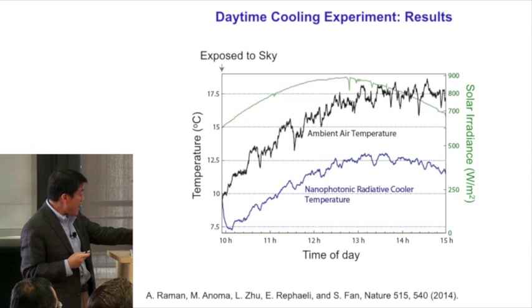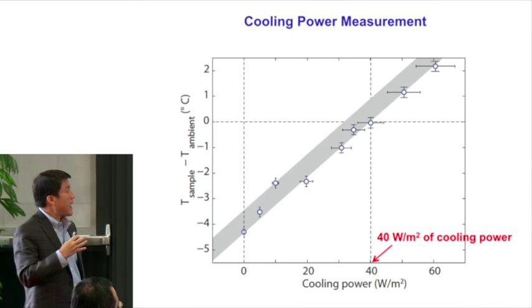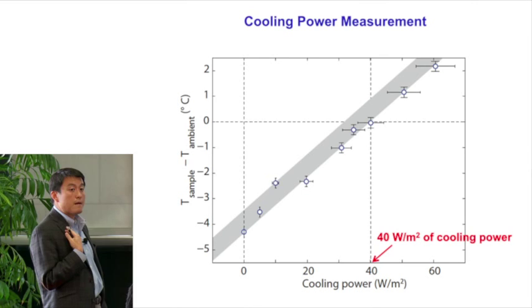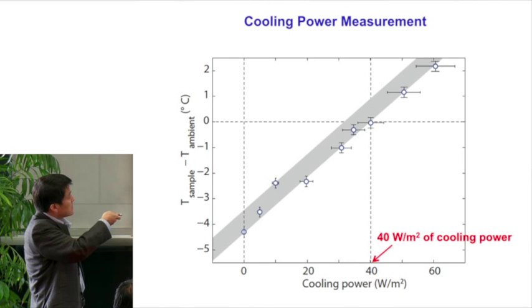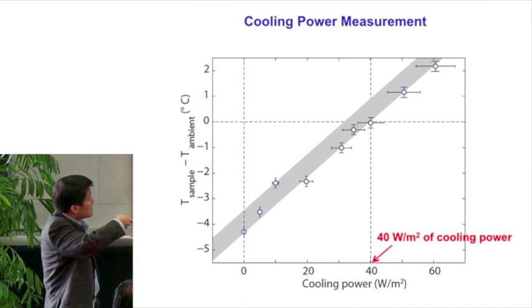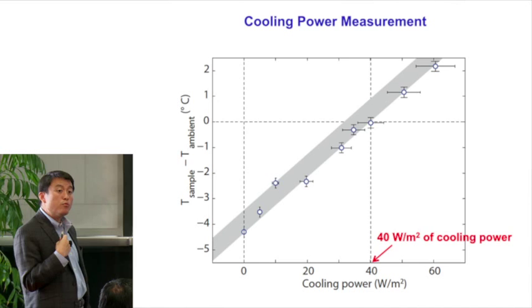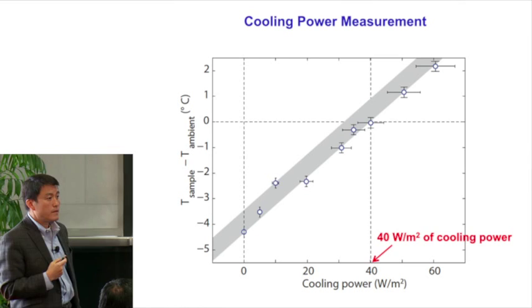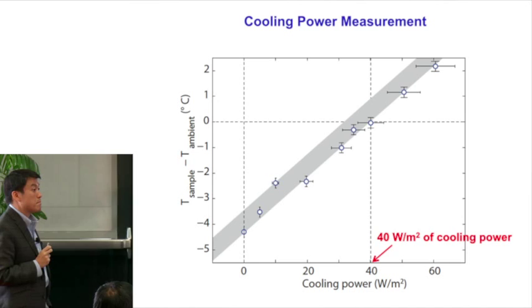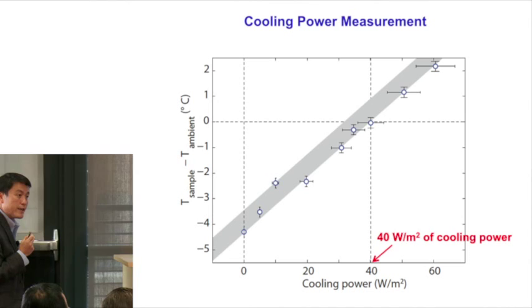We also did a cooling power measurement, by taking this device and intentionally putting in heating power, and seeing its temperature rise. So without the input electrical power, it has a temperature somewhere between 4 and 5 degrees Celsius below ambient. Put the heat in, and its temperature starts to rise. It took about 40 watts per meter squared of input heat power to drive the device temperature back to ambient. And that's a direct experimental measurement of the cooling power of the structure that we have built. So what we show here is a proof-of-principle demonstration of a device that actually cools under ambient sunlight.